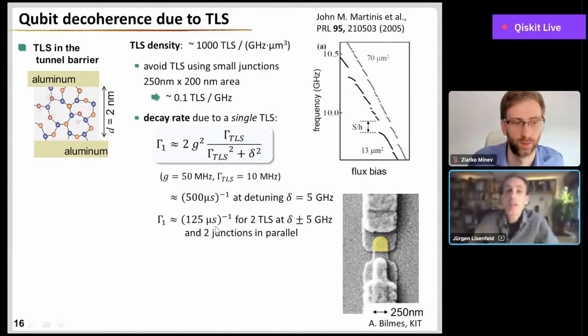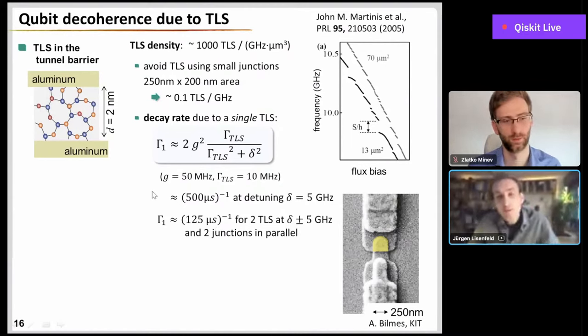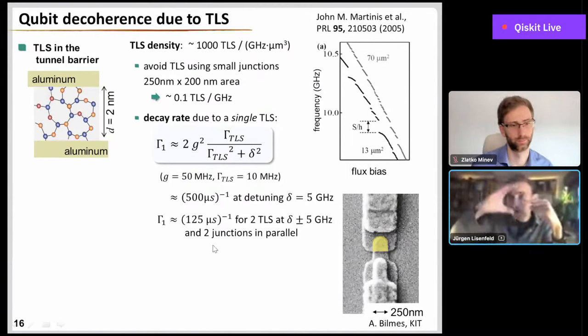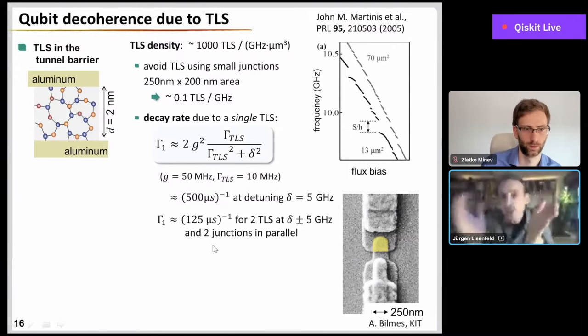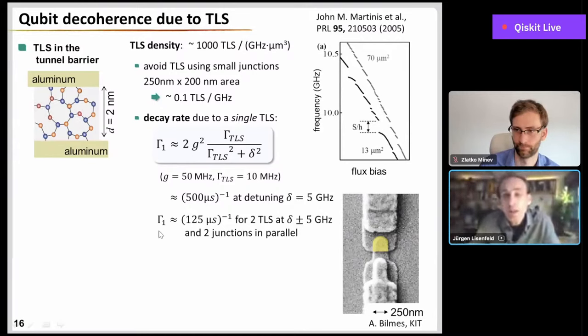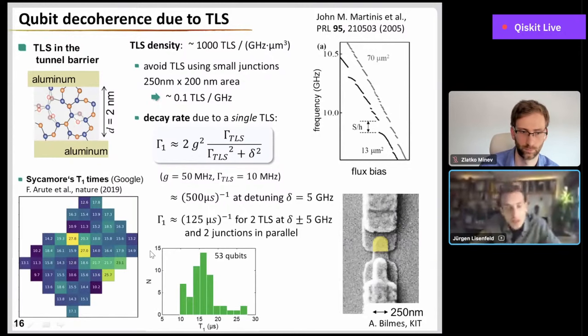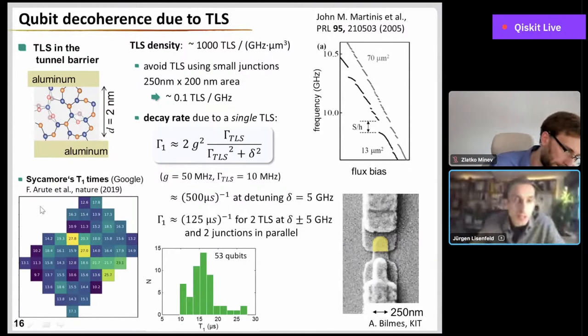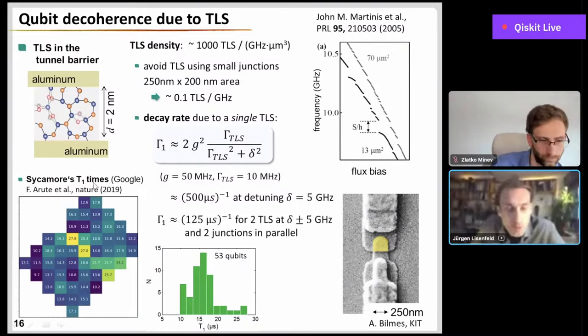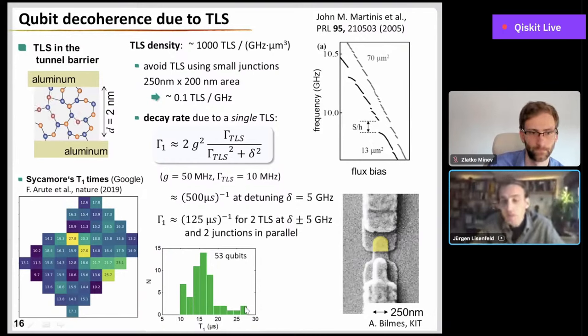T1 times. What you can definitely be sure is that this distribution, the frequencies at which these defects appear, will be very random. Each identically fabricated qubit will have the defects at a different position. And that's why you can expect that you get a certain spread of your T1 times across a wafer, for example. And this is what I see here. These are the T1 times of Google's Sycamore processor. And I also plotted the histogram here. So you see, you have typically a huge spread of T1 times, which can be up to plus minus 50% of this average T1 time.